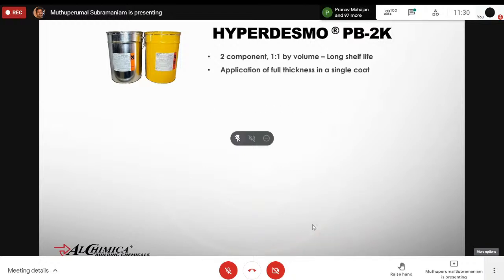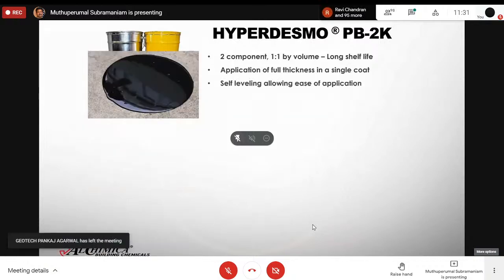It is a two component polyurethane system. Because of its two component system, it has better shelf life. It can develop to any thickness in a single coat. There's no need for multiple coats, which would raise the labor cost. The full thickness of the coating can be developed in a single coat. It's a self-leveling product, so there's no need for you to adjust the thickness based on the surface. It flows freely. It has a specific gravity lower than water, so it can flow to the profile of the roof slab or a podium slab and take the shape of the roof.